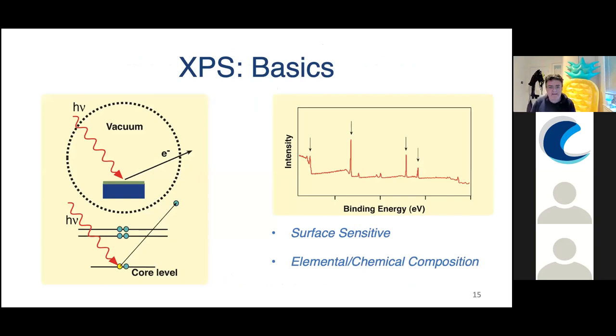So this shows you the basics of XPS. In XPS, you have impinging X-rays onto the surface of the sample, and that's a monochromatic beam, so it has a single energy, this beam of X-rays, and it ejects electrons out of atoms in the surface layers, out of different electron core levels in the surface, and generates these electrons called photoelectrons, which we can then count, the number of them depending on their kinetic energy. And we get spectra that look a bit like this, typically. So here's the intensity, that's the number of photoelectrons, and the binding energy is how strongly they're bound to the atom.